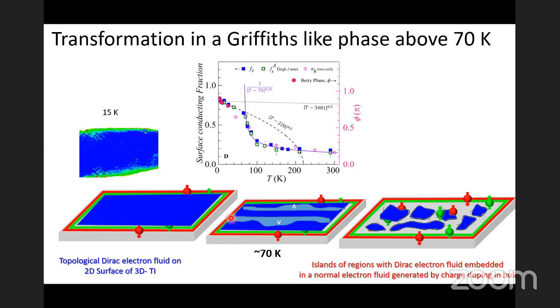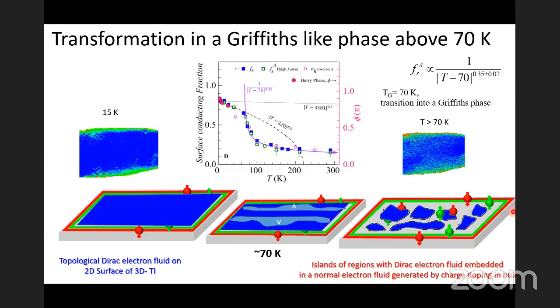So the system actually first breaks up into these patches, and then they break up further as you go to higher temperatures. And this is what we call a Griffiths-like phase transformation that we see as you go from this 2D surface state into a more inhomogeneous surface state inside the system. So this comes out as you look at the current distribution